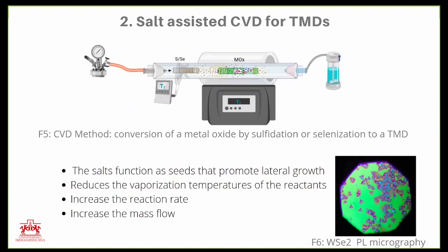Yeah, it depends on the mass flow. Sometimes we want to change temperature at a constant rate. So we have to let the reaction stay at the highest temperature of both precursors for 5-10 minutes. Sometimes if we let it more time, we have a constant layer.